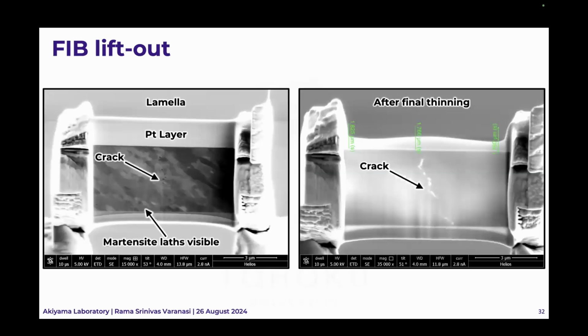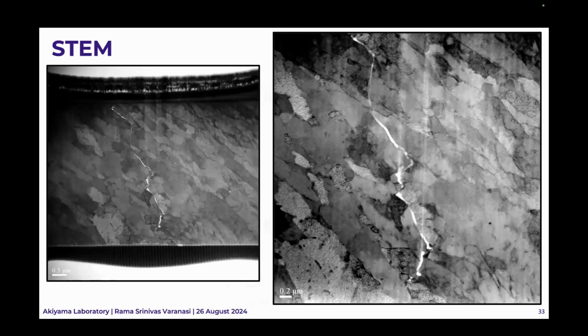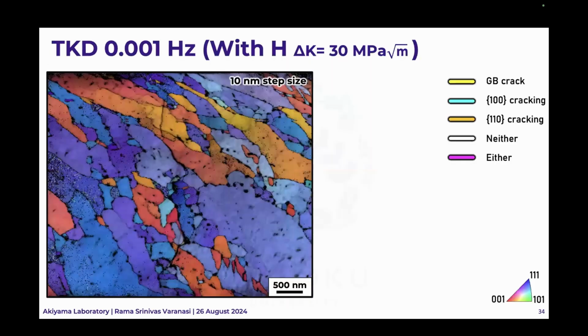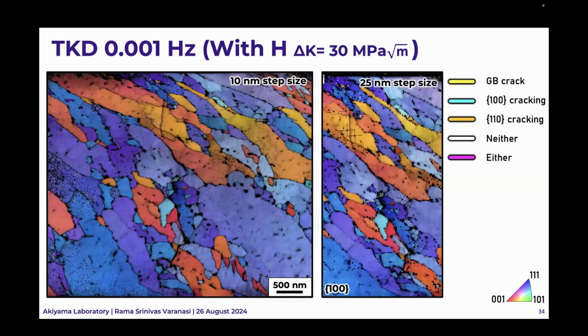So what we see is this is the beginning of milling, and this is after thinning the lamella. We can see this is the crack, and the crack propagation direction is into the lamella. And this is again showing some STEM images. We performed some TKD. The resolution of TKD would be about 8 nanometers. So this is the 10 nanometer step size, and this is 25 nanometers. The reason we went to 25 is, if you see here, this crack is slightly curved. This is coming because of drift, because of the smaller step size. So when we went to a little larger step size, we can clearly see that the crack is quite straight.